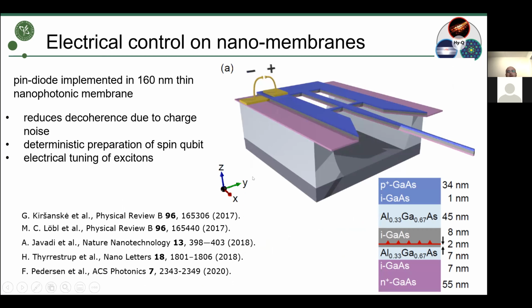And we can also add the electrical control on the quantum dot, and this is a very important thing. And you can do that by slightly doping this membrane. So this is actually something you can do during the epitaxial growth of these structures. You can add dopants. And so you can build, for example, a PIN junction here. And so when you apply a voltage to this PIN junction, you're applying an electric field to the quantum dots.